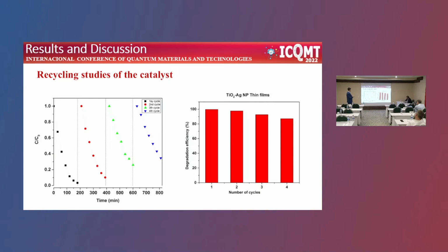You need to know perfectly if your photocatalyst has the same activity over time. In this case, the photocatalytic activity reduced only 5%, and this is normal because we studied these films with FTIR after the photocatalysis analysis, and we observe that the Rhodamine B, the pollutant, is in the photocatalytic center of the material, so it's normal, and this decrease is not really important compared to other decreases that, for example, lose 50%